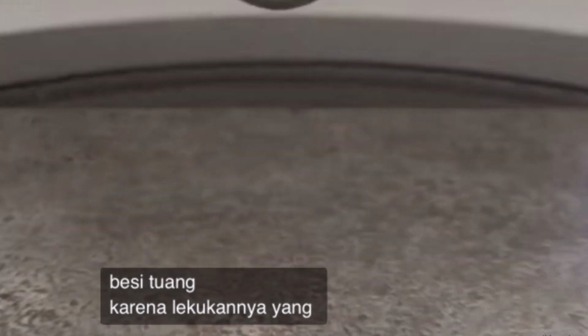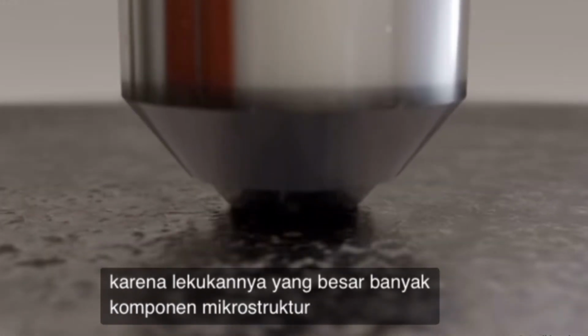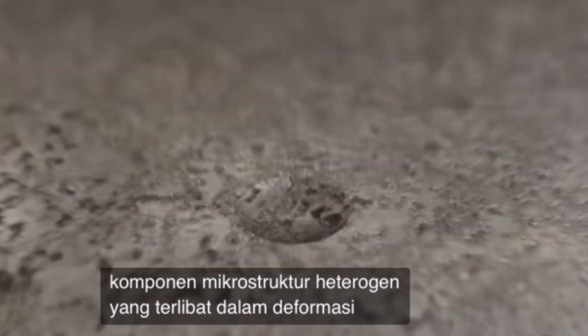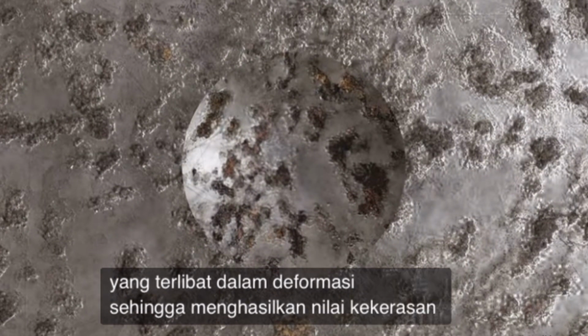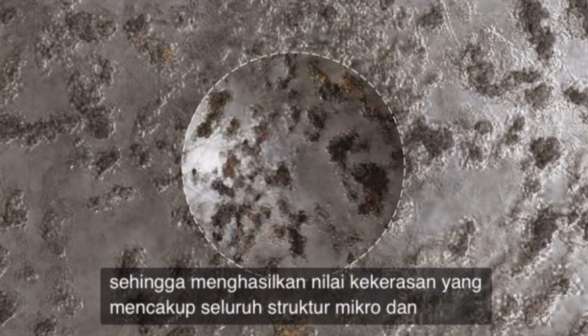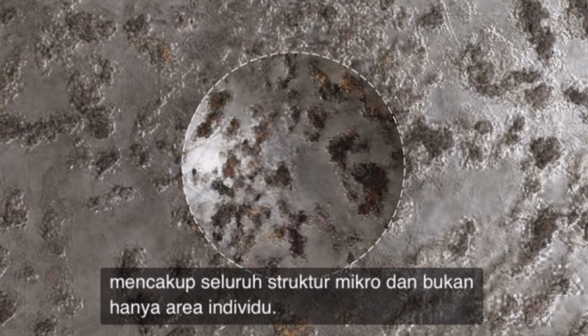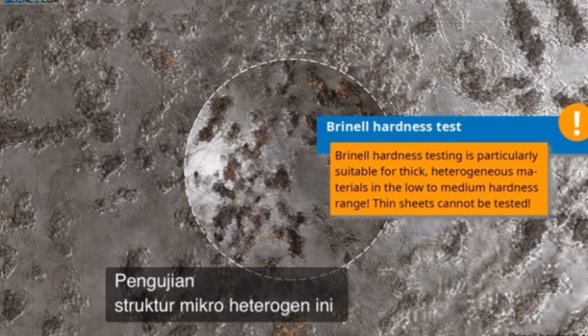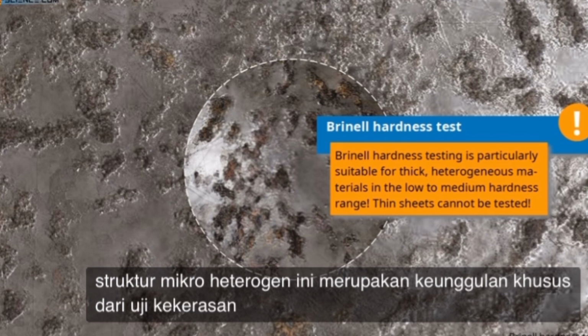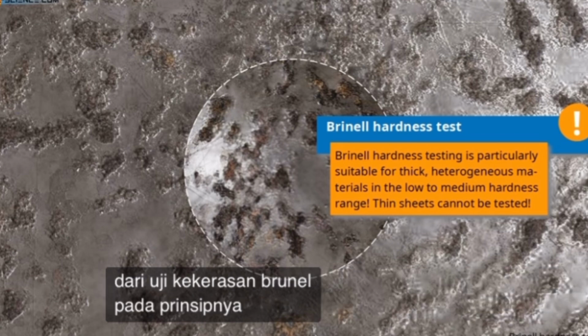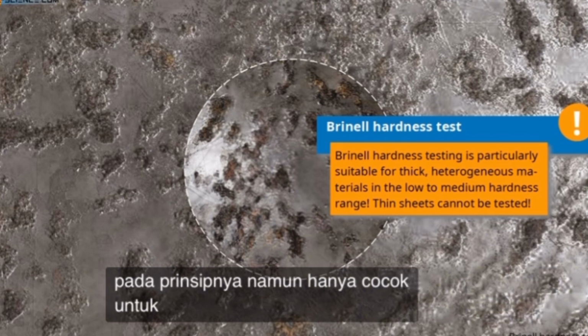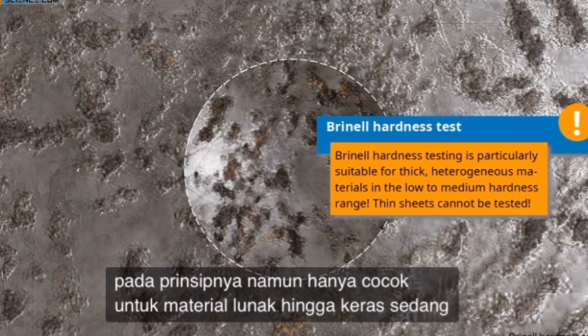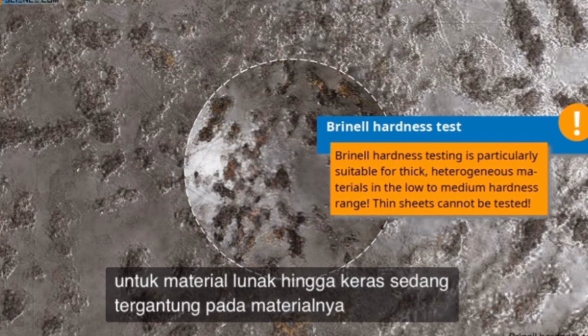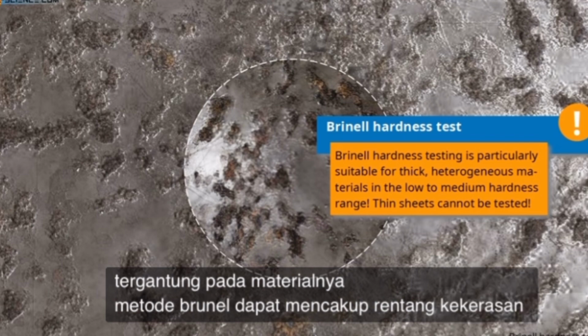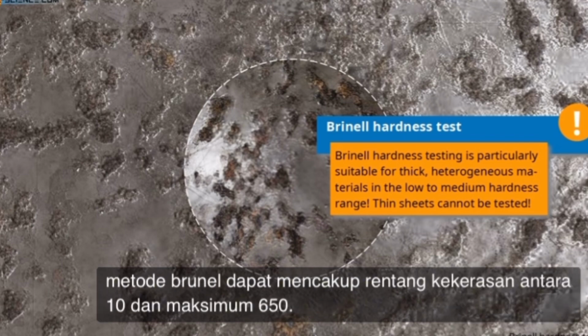Due to the large indentation, many heterogeneous microstructural components are involved in the deformation, resulting in a hardness value that covers the entire microstructure and not just individual areas. Testing heterogeneous microstructures is the special advantage of the Brinell hardness test. In principle, however, it is only suitable for soft to medium hard materials. Depending on the material, the Brinell method can cover hardness ranges between 10 and a maximum of 650.